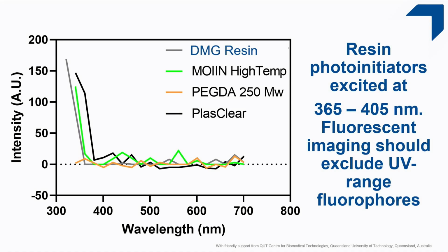And we heard one other thing, and this is a detection thing. It depends how your experience is with today's high-tech analytical equipment. But very often you have an issue because you want to detect something and that wavelength is blocked. And this is partially true with these resins. We use starter systems that work in a very specific wavelength range, and these can interfere with detection systems. However, and this is the good news, this is where research comes into play, you can overcome this issue. You can find ways or detection systems that detect the products, the molecules that you're focusing on, the reaction that tells you what is happening in a different range.